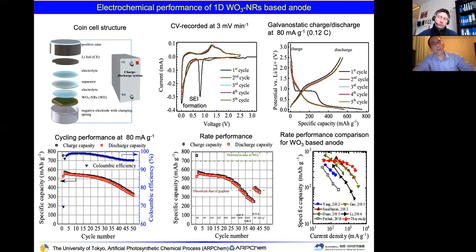So then we recorded CV, and as you can see here from the first cycle, there is an SEI formation layer, but during the second, third, fourth cycle, this SEI was already formed, and as you can see here, it's quite stable material. So what is the very interesting result here?